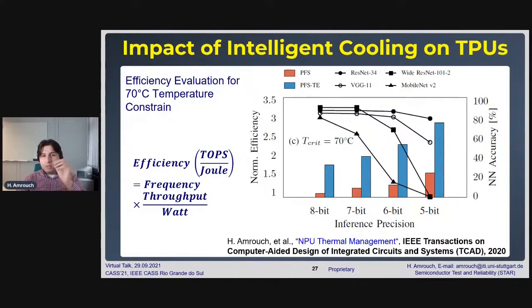Temperature constraint was here quite tough. It was like a 70 degree, which is really, really tight. And remember, originally you start from almost 120 degree or above even 120 degree. What we can see here, how for some models that can tolerate precision scaling, we are actually able to increase the efficiency by, let's say, around 3x, while the accuracy drop is very small.